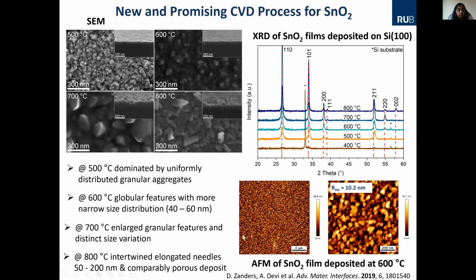When we look at the atomic force microscopy images, you see the roughness of the surface on the silicon substrate is around 10.2 nanometers. This is pretty high. Maybe you recall when I told you about aluminum oxide, it was around 0.3 nanometers. That is good for gas barrier applications where you want a very smooth surface, no holes, no grain boundaries, nothing. Absolutely amorphous film. Here you want a crystalline material with high surface area, because for sensing applications this is more relevant. So this is just to show you an example where surface roughness is much higher. Of course, the temperature is much higher. This is a CVD grown film, not ALD, but around 800 degrees you can have intertwined elongated grains, which could be interesting for sensing applications.